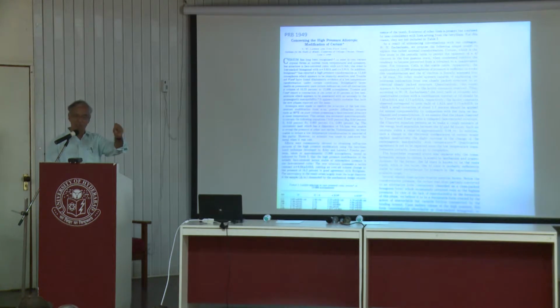You start with one 4f electron. Under pressure, you are losing the 4f electron. Therefore, under pressure, the valency is changing. So-called, in the old terminology, valency is changing from 3+ to 4+. He said it is not absurd because cerium dioxide, CeO2, has valency 4+. I mean, in the old terminology. Therefore, that is a possibility.